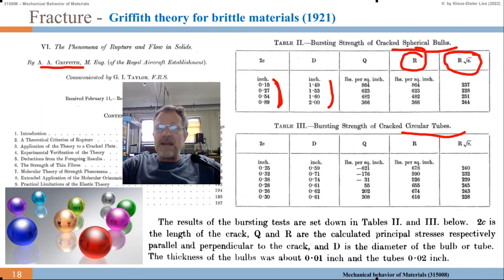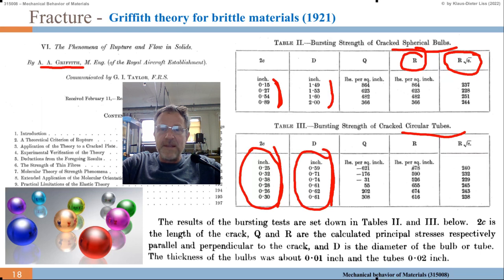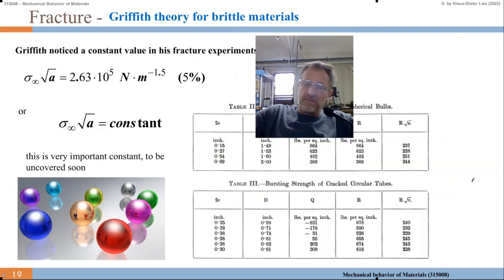He did the same for the pipes, the circular tubes. He has different diameters, not varying that much, and different crack lengths. He calculated the hoop stress per square inch to apply, measured them, and found similar values: 240, 232, 229, so around 240. You can go through the numbers.